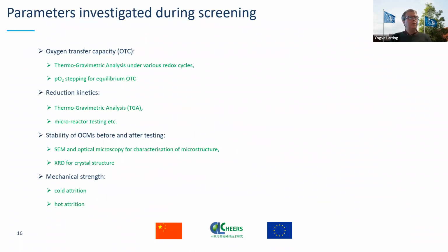Parameters investigated during screening were oxygen transfer capacity by thermogravimetric analysis in the various redox cycles, stepping for equilibrium oxygen transfer capacities. We also did the reduction kinetics in thermogravimetric analysis and micro-reactor testing. And stability of the OCM, we checked before and after testing by SEM and optical microscopy for characterization of the microstructure to see how it degrades as well, and also with XRD in some cases where this is needed. And we also did some mechanical strength tests, both by cold attrition and hot attrition.